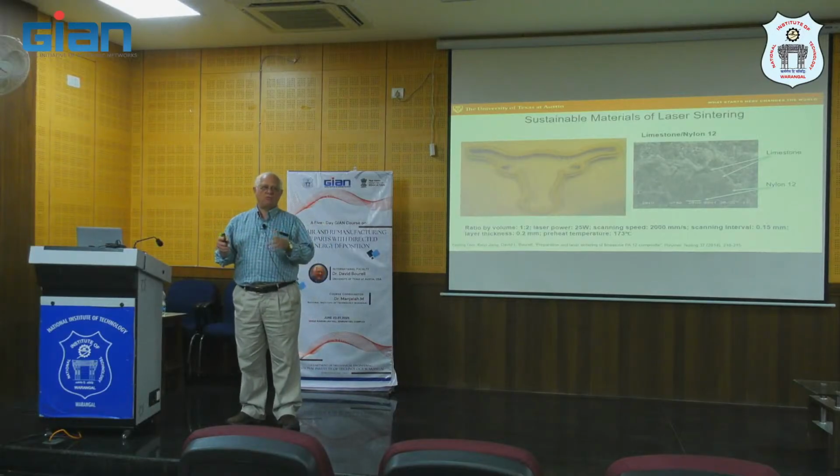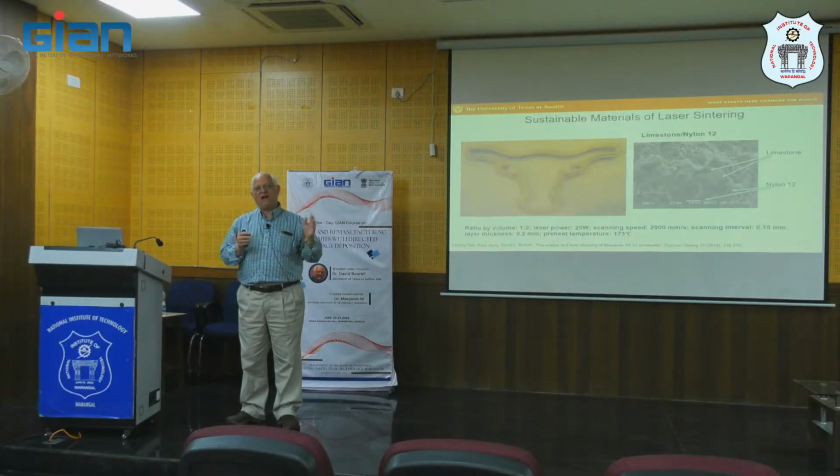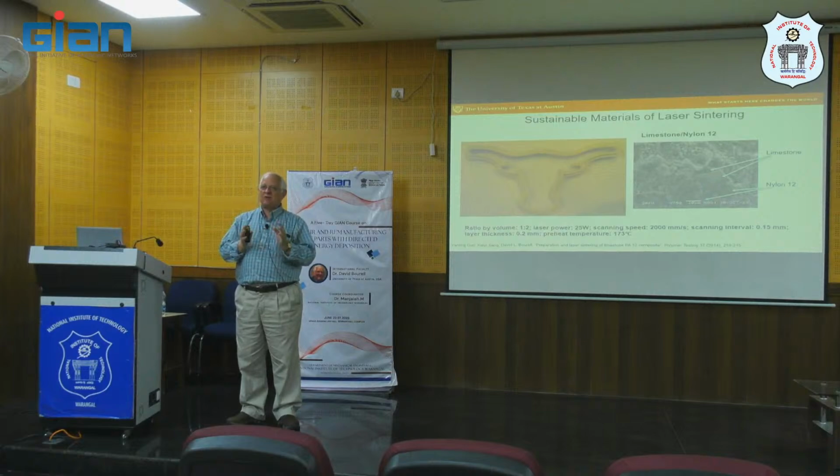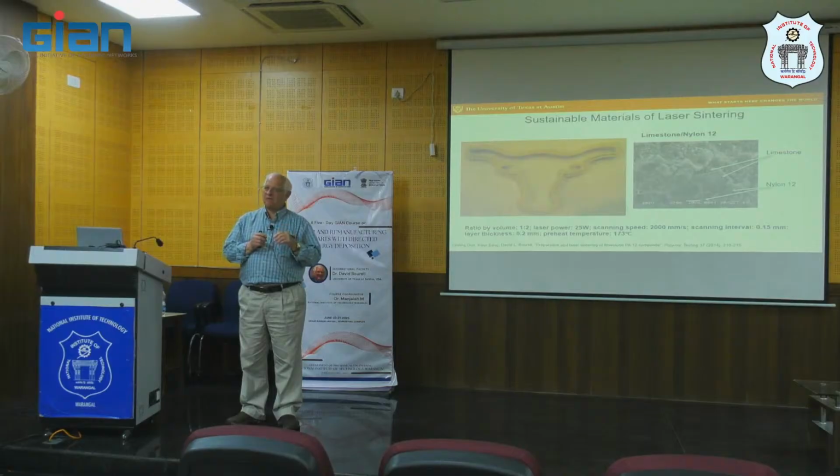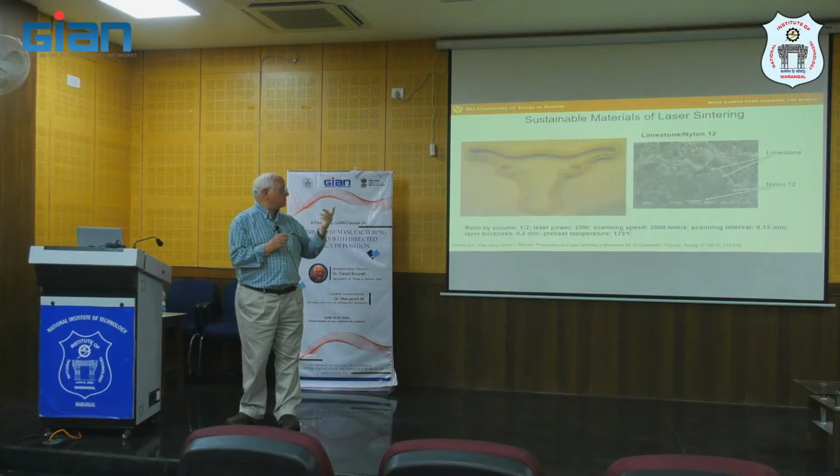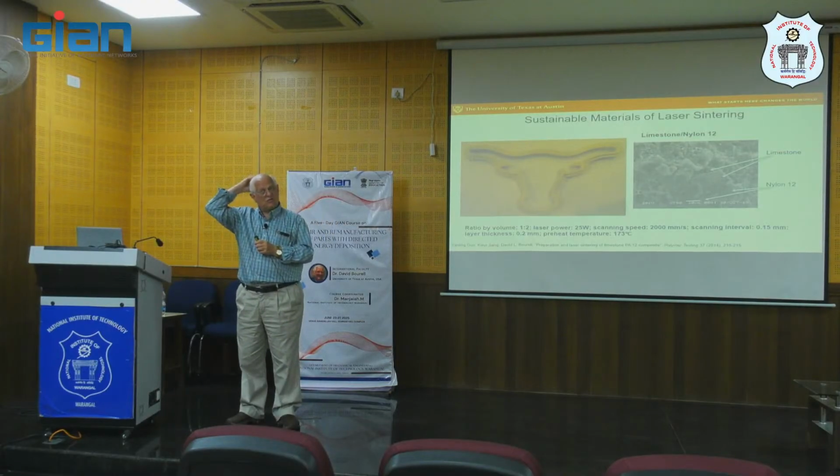Most of it was used for road paving, and it was in the form of pebbles in size. But the finest limestone powder that they put together was about this size. We're talking 10 to 30, 40 microns, which is a great size for us.